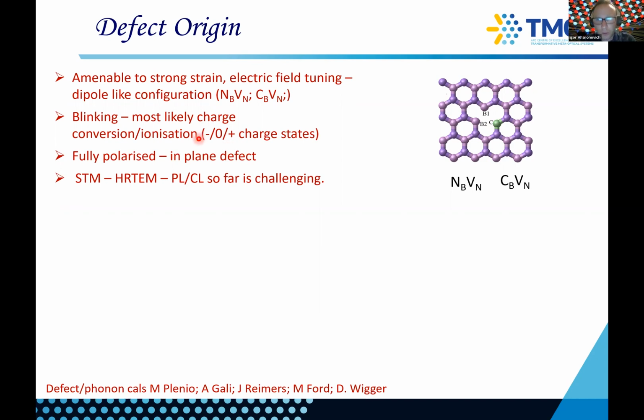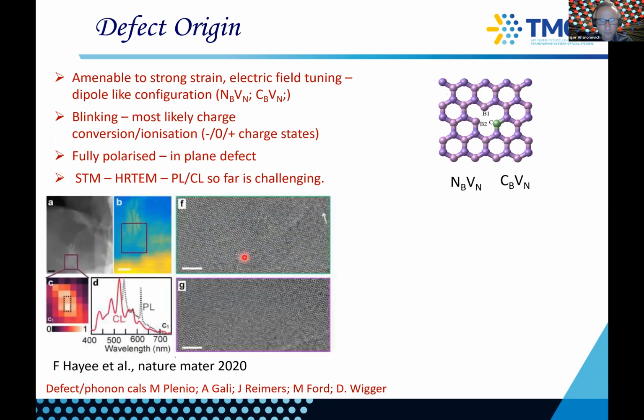Now, when we started to work on hBN, the immediate feeling is, well, you have a 2D material, which is atomically thin. Why don't you just go to a high resolution TEM, find your defect and look at the defect? And so we all thought like that. It actually turned out to be very hard, because even though you can find the same spot that you did your photoluminescence from, and you can record also a cathodoluminescence image from exactly the same spot as shown here, under the same exact magnification, you would have about 100, if not more, defects. And so one of them is shown here. It's a vacancy with an arrow, but you would have hundreds, if not more, defects.